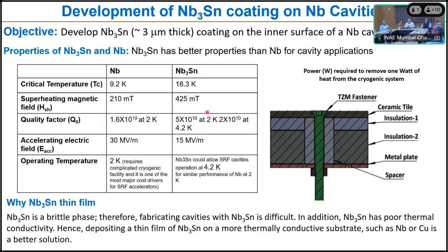So what we do is coat niobium with Nb3Sn. Nb3Sn has the property that, if you look on the table, niobium has a critical temperature of 9.2 Kelvin, while Nb3Sn has a critical temperature of 18.3 Kelvin. Looking at the superheating magnetic field and all the properties, Nb3Sn offers much superior properties. Now, Nb3Sn can be very quickly coated on Nb because the properties are matching quite a bit.